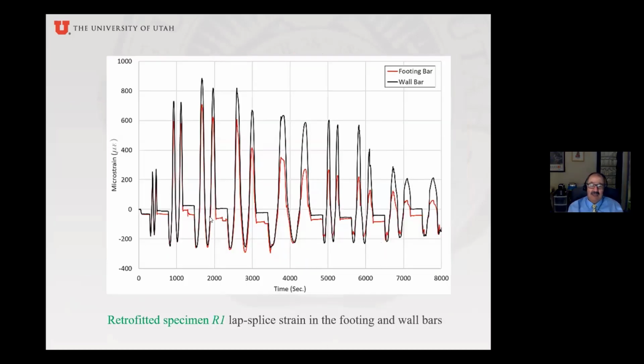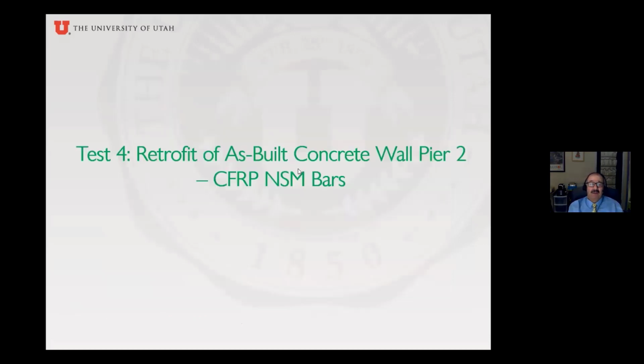The lap splice actually wasn't too bad, because as you can see here, the footing bar and the wall bar, first of all, the strain is very small. They never yielded. So it's almost like the steel wasn't there. It didn't matter if it was there or not. So I would say that the retrofit was successful.